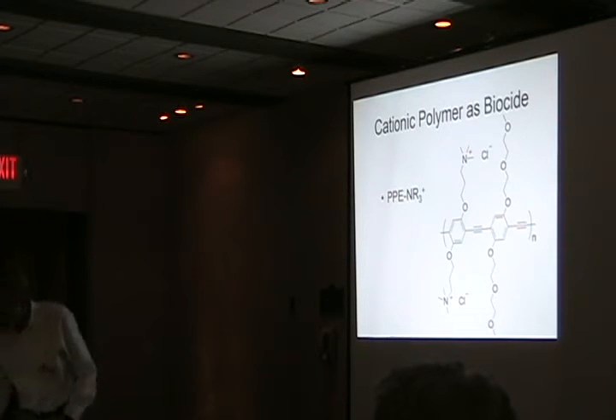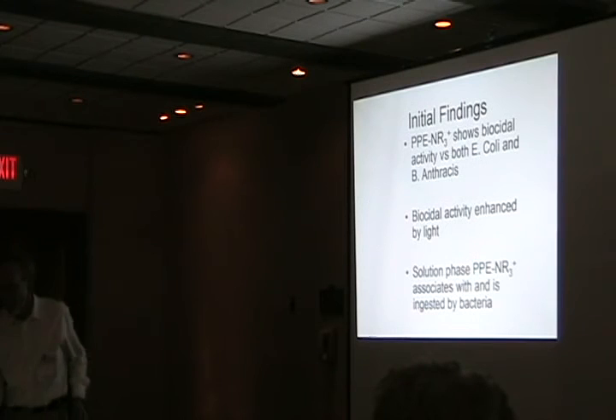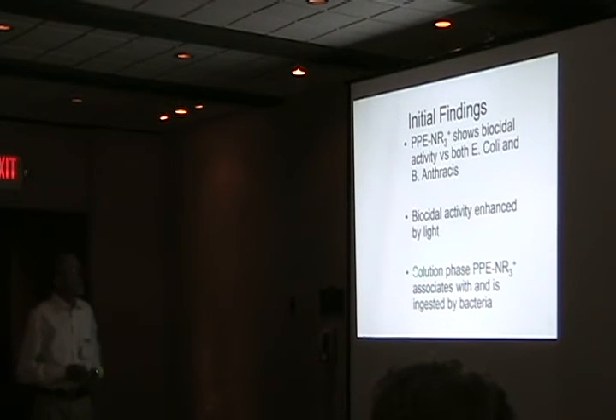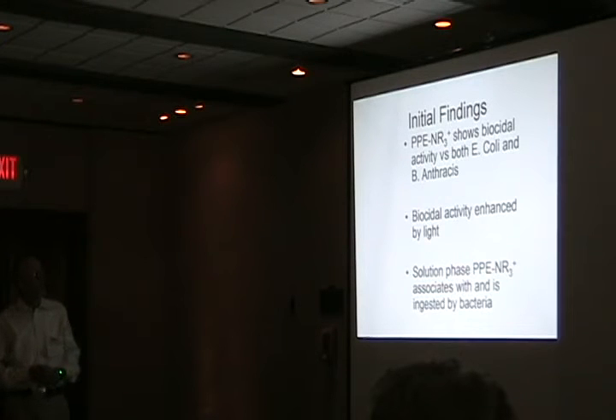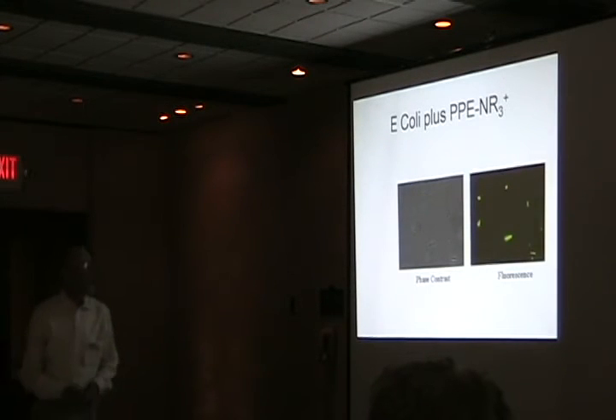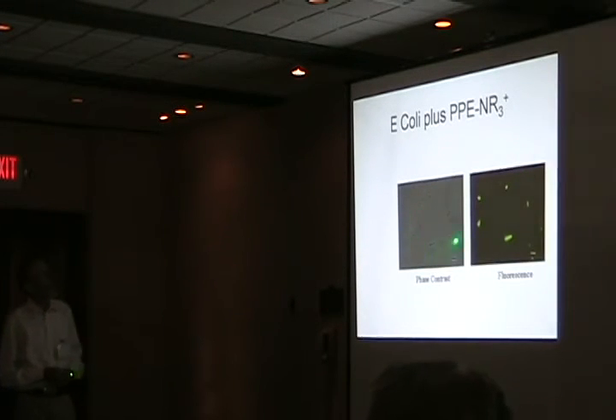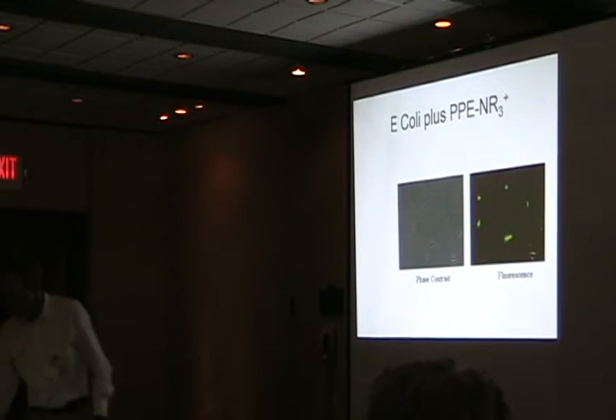So the question is, why and how much? Anyway, what we found is very clear: if we just take the polymer in solution and add a suspension of bacteria with it, just mix it, shake, and so forth, the polymer coats the bacteria and maybe even is ingested by them. For example, here's a sample of E. coli that's been exposed to the polymer by phase contrast microscopy, and then here's the same suspension, the same area looked at by fluorescence microscopy. You can clearly see that the fluorescent spots associate with the bacteria, and the bacteria is now fluorescent because of its coat of the polymer.